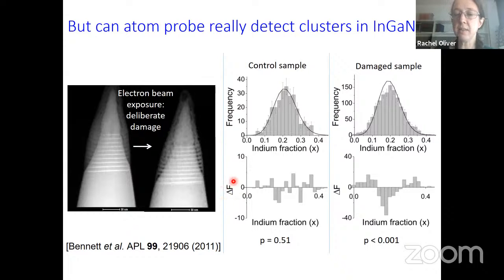And then I've taken the difference between the actual frequency seen in the experiment and the predicted frequency from my random alloy picture. And what you can see is that my difference plot looks very like random noise, okay? So there's no clear trend, no lots of regions of high indium content or low indium content. But if we look at the damaged sample, that same difference plot is showing excess regions at the low indium content end, excess regions at the high indium content end, and not enough regions with the typical indium content. So that's a signature that this is not a randomly distributed indium content.